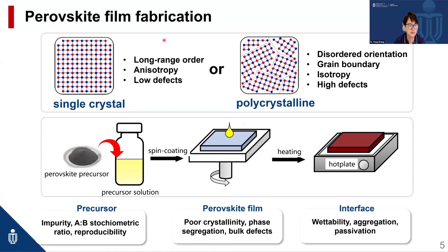But for perovskite films used in solar cells, normally most films are polycrystalline, and they have drawbacks of disordered orientation and grain boundaries that result in defects inside the perovskite film. Although we say perovskite has some certain level of defect tolerance, if we want to fabricate higher efficiency devices, removing these kinds of defects is very important.